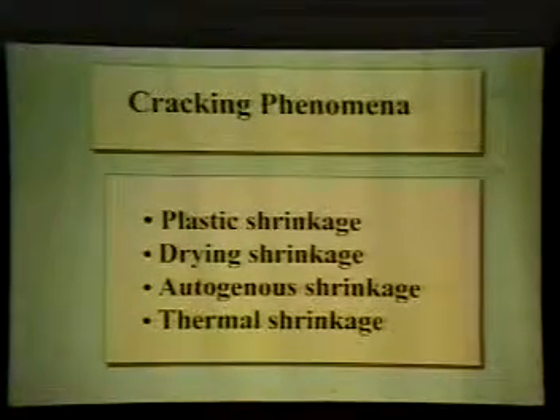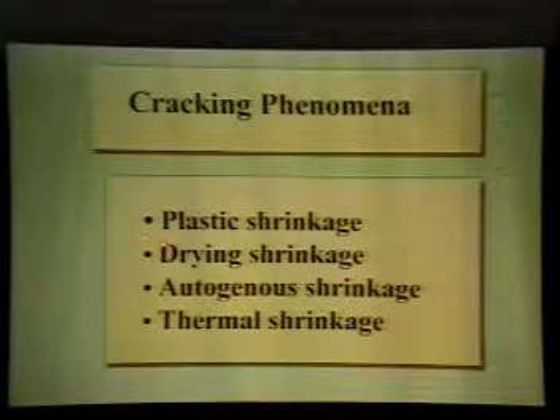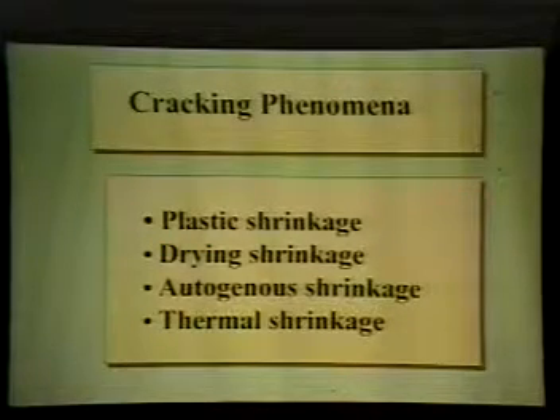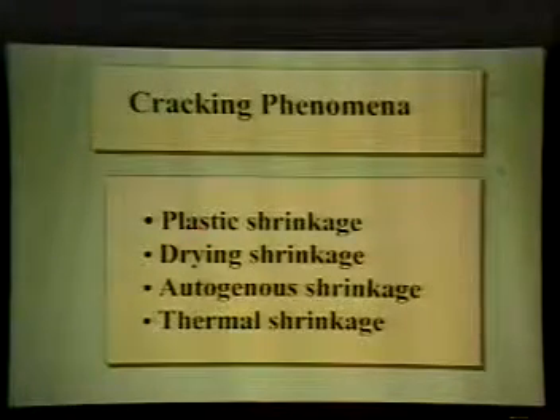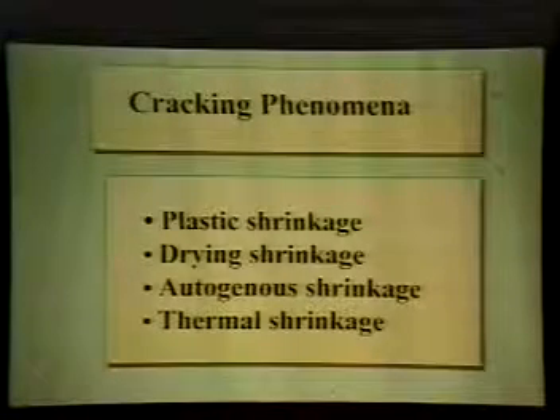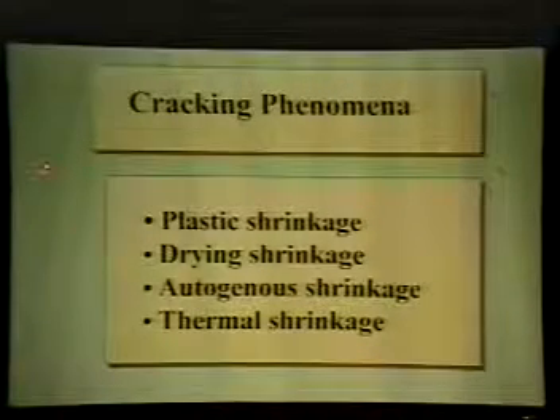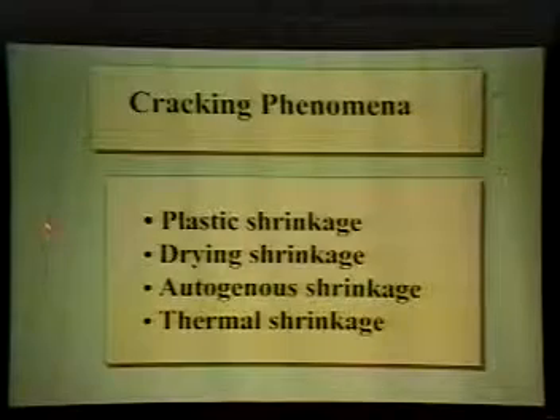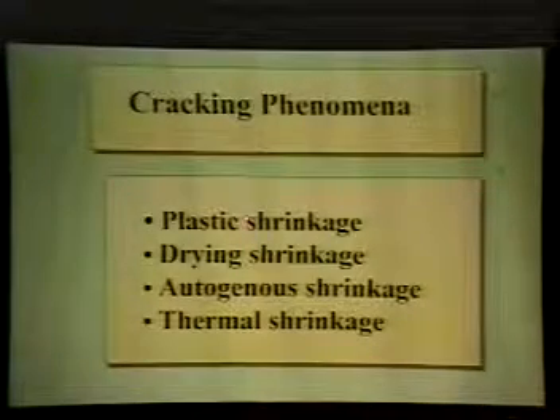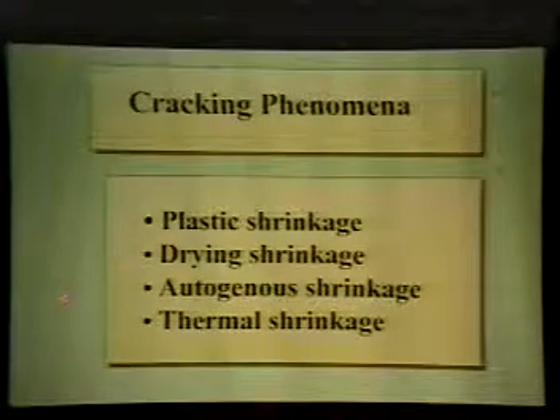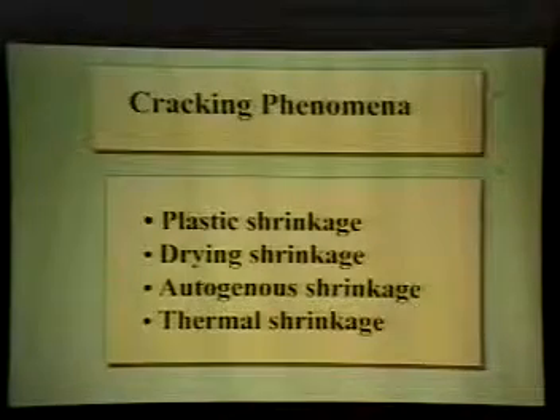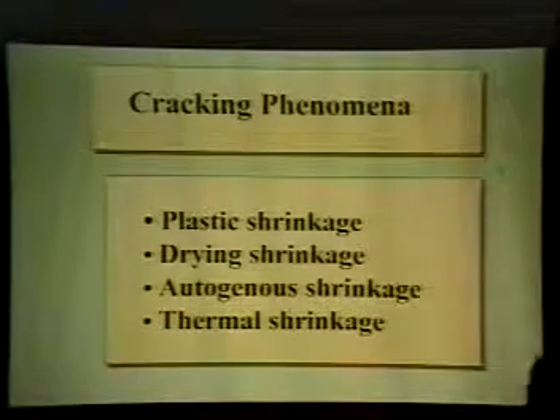Cracking phenomena has been creating a lot of research these days, because with fast track concreting practices, cracks can be a problem. There are different types of cracks. You have plastic shrinkage cracks on the surface, drying shrinkage, autogenous shrinkage, and thermal shrinkage. And these can be distinguished under the microscope. What you see here is a drying shrinkage crack. Very short cracks, very fine cracks.